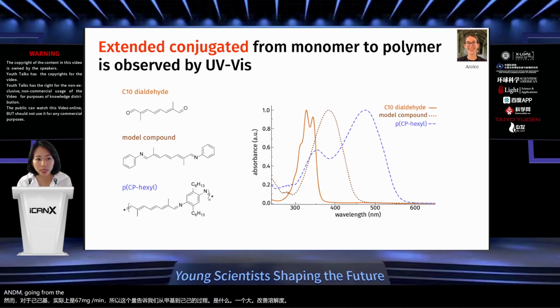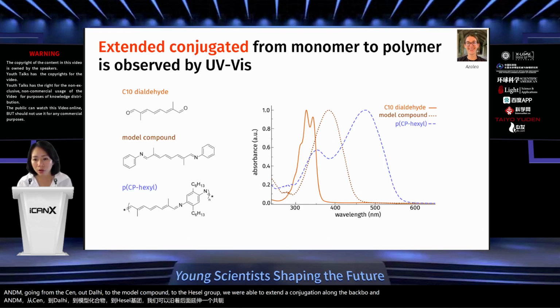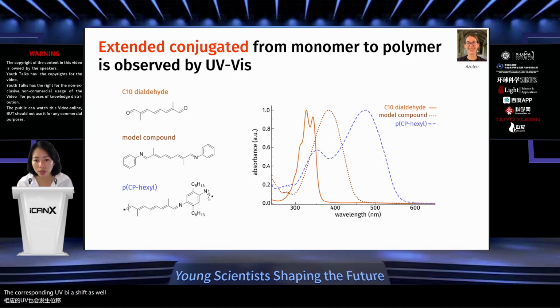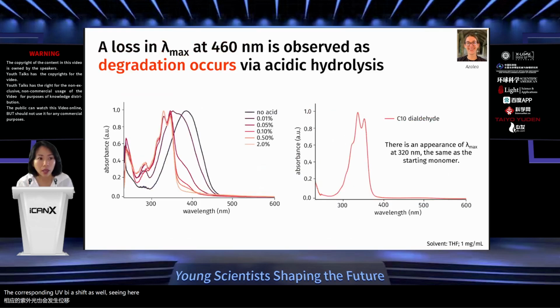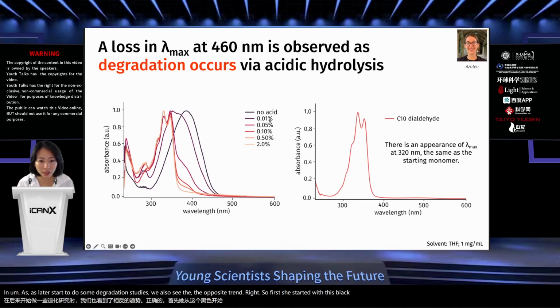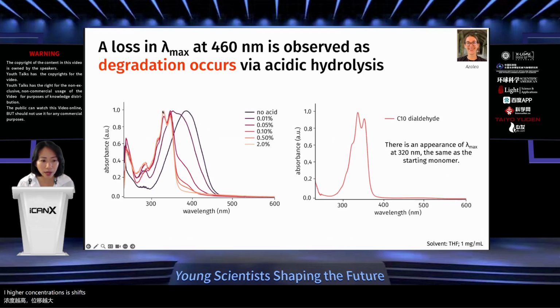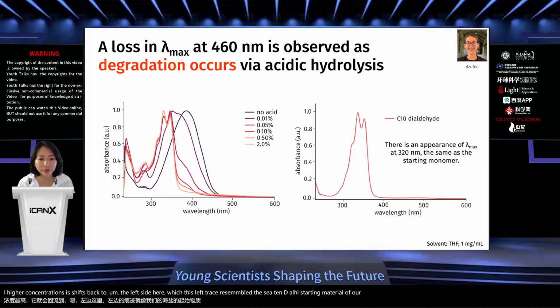Going from the C10 dialdehyde to the model compound to the hexyl polymer, we were able to extend the conjugation along the backbone and saw the corresponding UV-vis shift as well, seen here. And as Azalea started to do some degradation studies, we also see the opposite trend, right? So first she started with this black trace here. As she added more acid, at higher concentrations, it shifts back to the left side here, and this left trace resembled the C10 dialdehyde starting material of our monomer.